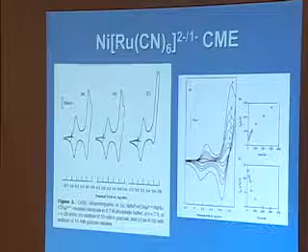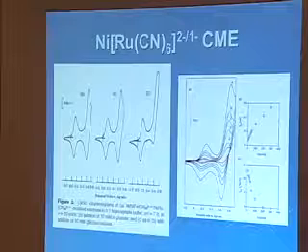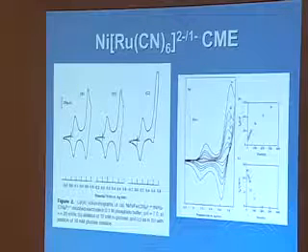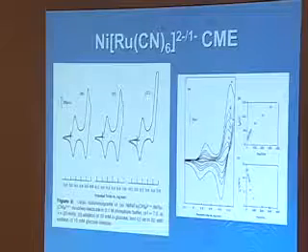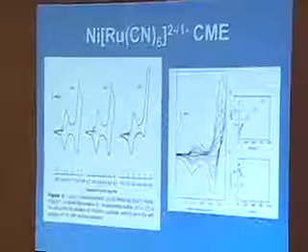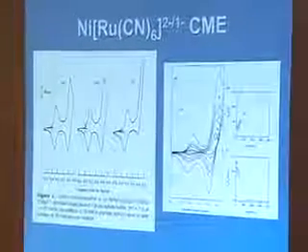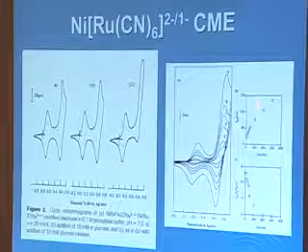In fact, it has two purposes here. Number one is stopping the corrosion of the nickel electrode, and number two, it's an internal standard. I know exactly how much is there. So there's your mediated charge transfer going on, very easy to see in this case. Don't even need a scan rate dependence, but of course you can't show up in my office without a scan rate dependence, so there's the scan rate dependence.